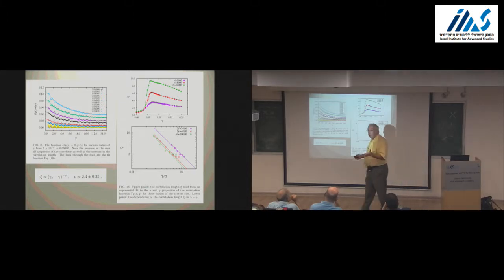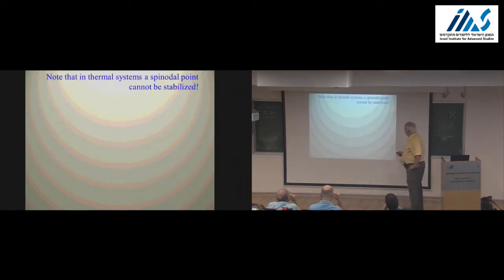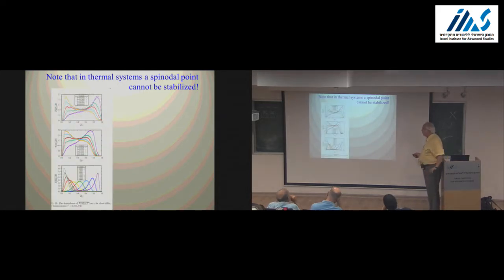Now you'd ask me, well, temperature zero, what happens when the temperature is finite? Well, in thermal systems, as I said before, a spinodal point can never be stabilized. So let's see what happens. Here, I repeat these PDFs for the average Q12, and you see that there's a nice transition. You put a low temperature, and it begins to muck it up. You can still see this. At a high temperature, you lose the transition altogether. There's always one average PDF that is becoming this and this.